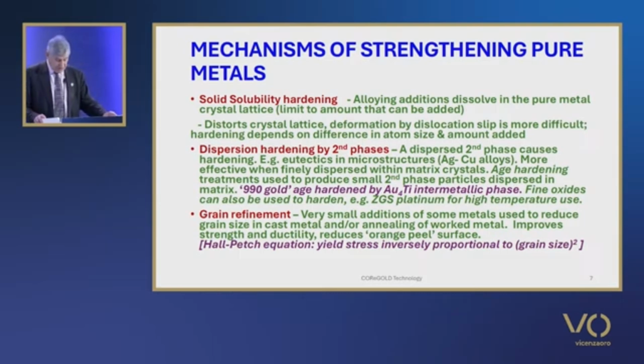Grain refinement. Very small additions of certain alloying metals are often used to reduce the crystal or grain size of precious metals and their alloys. This can result in improved ductility, reduced orange peel surface on worked material, and improved strength. The hardening effect of grain size of metal is described by the Hall-Petch equation, in which the yield stress is inversely proportional to the square root of the grain size.